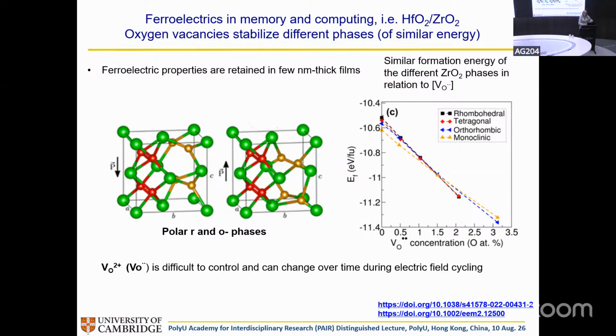Then you might not have a ferroelectric phase because only the polar phases, rhombohedral and orthorhombic, are ferroelectric. So if you start forming monoclinic or tetragonal after cycling and losing some oxygen, it's not going to be ferroelectric anymore. And then the thing doesn't work. And so that happens a lot. This cycling, as you cycle it, the oxygen does move and you do see that things degrade. So the question is how to control the material to keep the oxygen in, to control the phase you want.